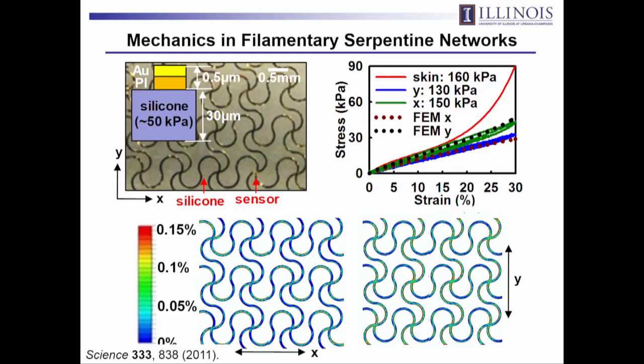So if you want to do an integrated circuit, for example, you exploit geometries like this, these filamentary serpentine mesh type structures. So here you're exploiting not only out-of-plane buckling, but also in-plane buckling by virtue of the filamentary serpentine design. And so you can make a composite. Hard materials are providing the electronic functionality. There's a soft silicone substrate here. If you pay quantitative attention to the detailed mechanics of how this hard, soft material responds to applied strain, you can optimize the layouts to create an effective material that has stress-strain behavior quantitatively matched to that of skin.